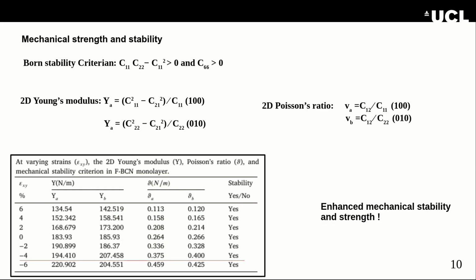Further, we tested the mechanical strength and stability. The Born criterion was used to see the stability criteria. First, we calculated the elastic tensors, and we computed the 2D Young's modulus and Poisson ratio using these relations. We found that the material exhibits almost similar strength to the pristine counterpart. And not only that, when we apply strain along the biaxial direction, we found that the compound can tune the mechanical behavior.